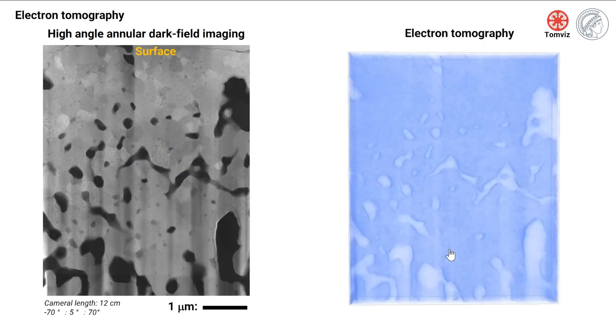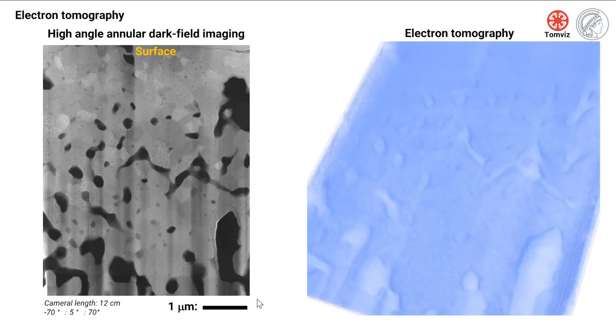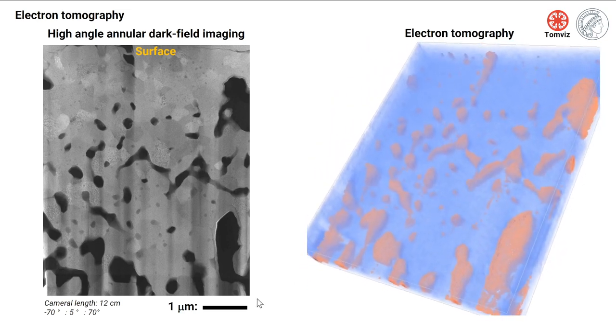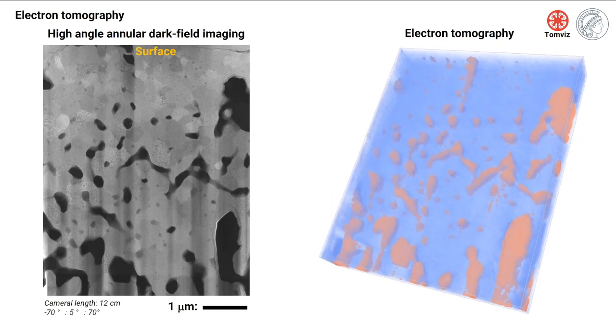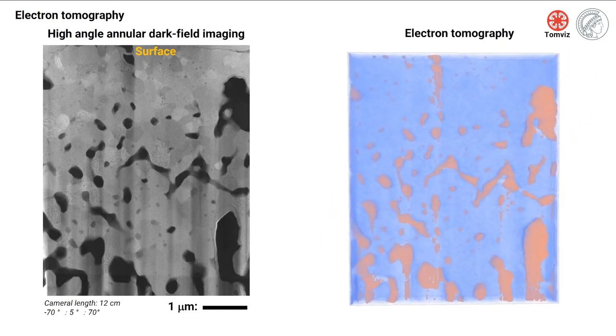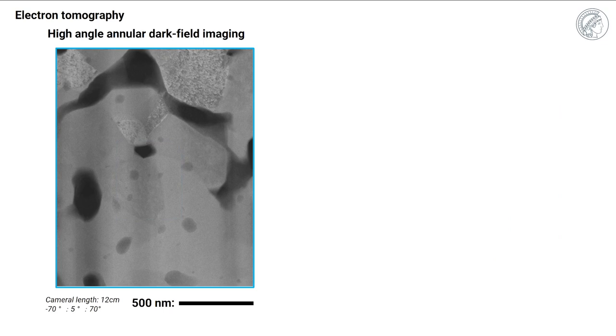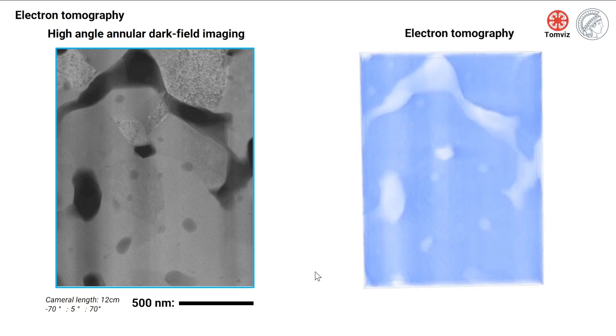We also look at the characteristics of these pores that form at very high resolution. This is high angle annular dark field imaging. And through this electron tomography, we aim to study not just the distribution of the pores, but also how they are connected. That means how they percolate. This is a very important information that we need to better understand how the gas transport in the material takes place. Here you see a complex polycrystalline structure around such pores that form.